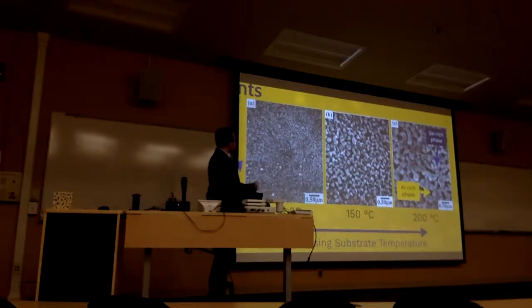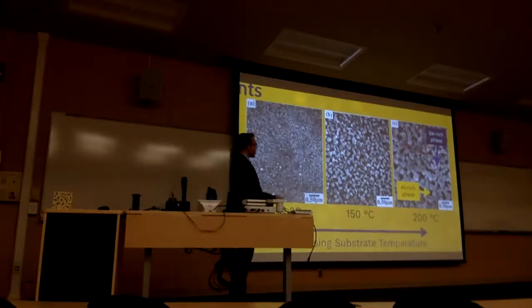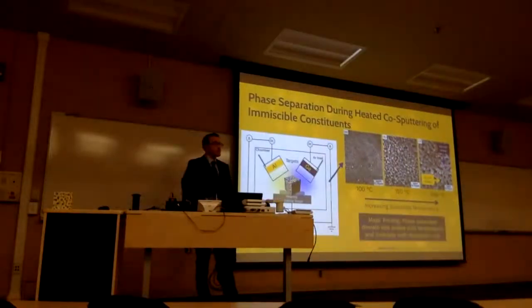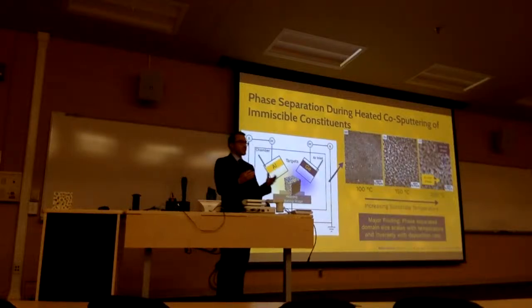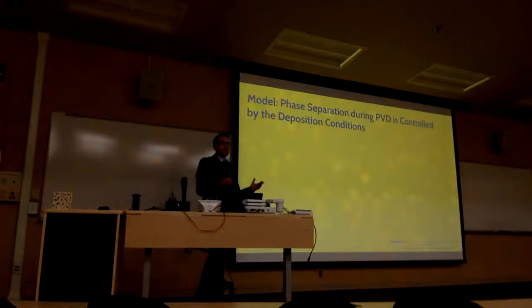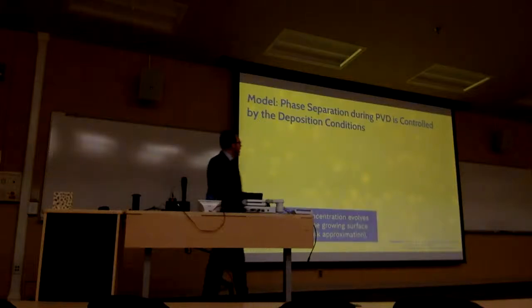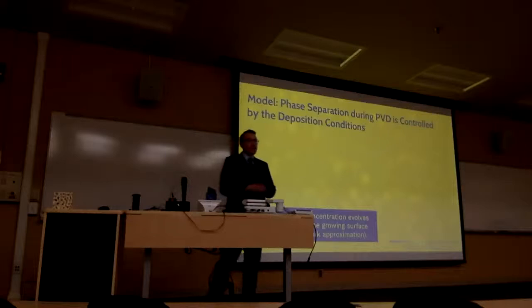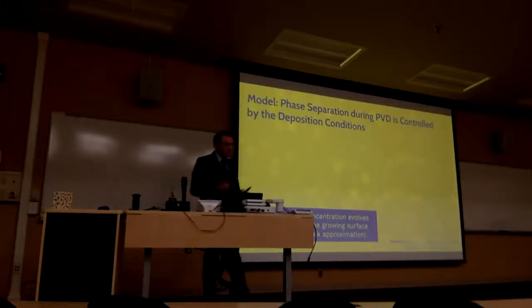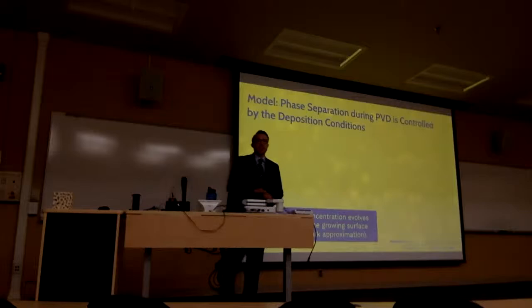What I hope you can point out here is that the sample coarsens as a function of substrate temperature. The domain size of the phase-separated architecture actually grows as a function of temperature. And that was one of the major findings of this work, is that we could actually control that phase separation process using the deposition conditions. So they actually tried to model this system analytically using one initial assumption, and that is that everything that's evolving, the concentration, is happening on the surface, the growing film surface. As in, the deposition time and temperature are such that no bulk diffusion is happening during deposition.